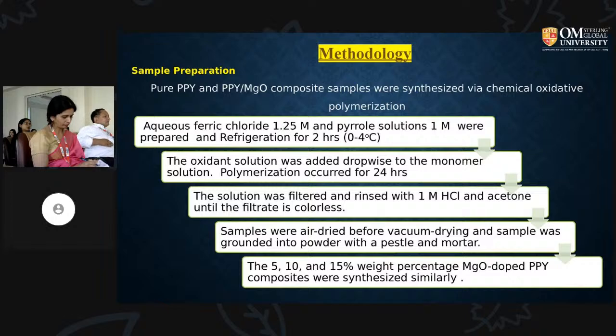After enough time, the solution was filtered through filter paper. Rinse the yield with 1 molar HCl and acetone until the filtrate is colorless. This yield was air dried before the vacuum drying. The dried sample was ground into powder with pestle and mortar. The 5, 10, and 15% weight percentage magnesium oxide doped polypyrrole composites were synthesized.